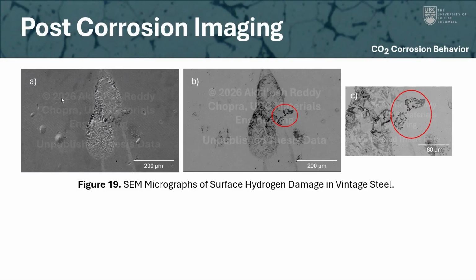I also performed, as you can see here, SEM images on post-corroded samples. So these are the blistered samples immersed in the CO2-rich media. And what is very interesting is we see localized attack, right? So in all three images, which is essentially the same location, these were all exposed to our electrolyte. But we can see the base steel, right?